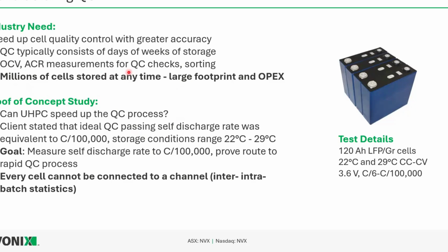We can't put every cell, a million a day coming off of a gigafactory line, onto a channel and measure it during QC. So we have to do these quick one-off checks after storage periods. These millions of cells stored at any given time create a large footprint and OpEx for companies. So this proof of concept study was to see if UHPC can speed up this QC process. We had a client state once that an ideal QC passing self-discharge rate would be equivalent to something like C over 100,000. If we were able to detect whether a cell was self-discharging at that rate quickly, then this would really rapidly speed up their QC process.